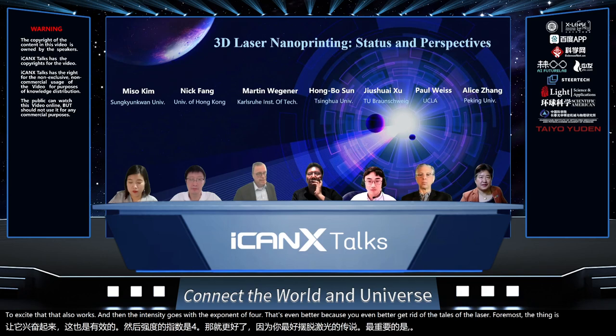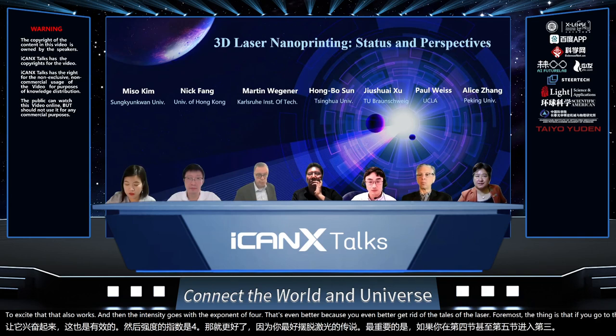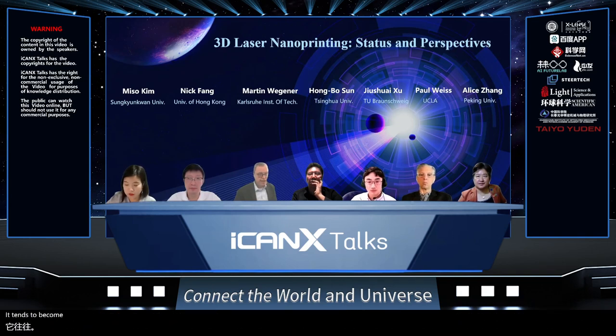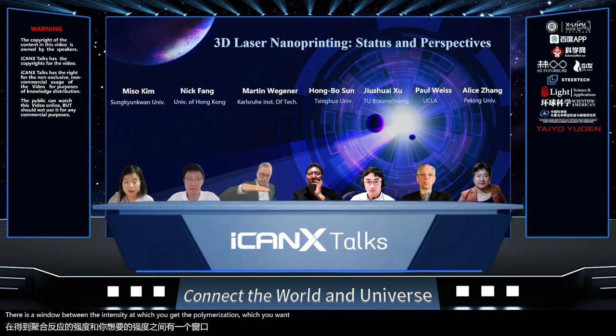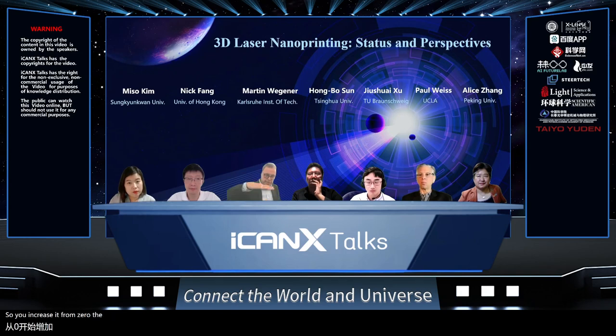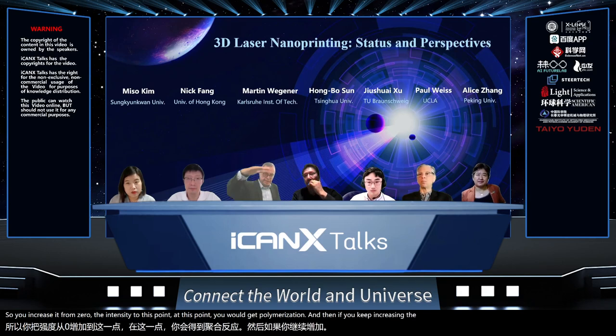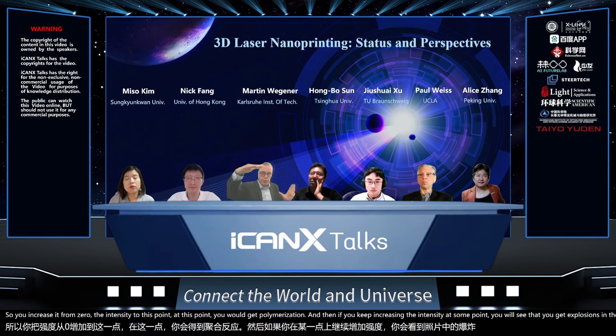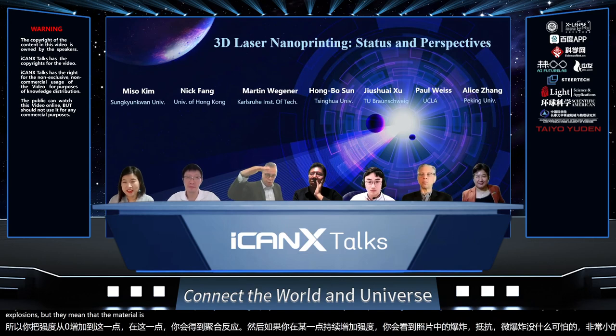The thing is that if you go to third order, fourth order, or even fifth order processes, which we have done, it tends to become a little bit more critical. There is a window between the intensity at which you get polymerization, which you want. Say you increase the intensity from zero to this point. At this point, you would get polymerization. And then if you keep increasing the intensity, at some point you will see that you get explosions in the photoresist, micro explosions, nothing terrible, very small explosions. But they mean that the material is destroyed. You do not want this.